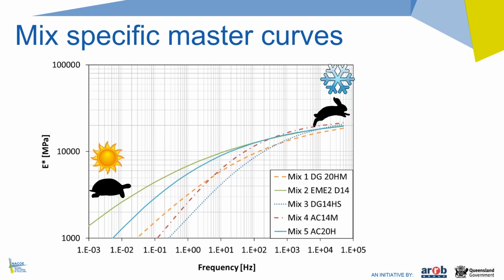Right, then if we have done that for different mixes, we'll get different outcomes. So this slide shows you mix-specific modulus master curves for different mixes tested as part of the TMR research program. The top line are the results for an EME2, and as you can see, that mix has by far the highest modulus, especially at the higher temperatures, and the turtle represents slow-moving loads. So on the left part of the graph, you can see the high temperature slow-moving load space. EME2 has got the highest modulus, and then the DG14HS, which is a mix with a polymer-modified binder in it, has got the lowest modulus of the lot.